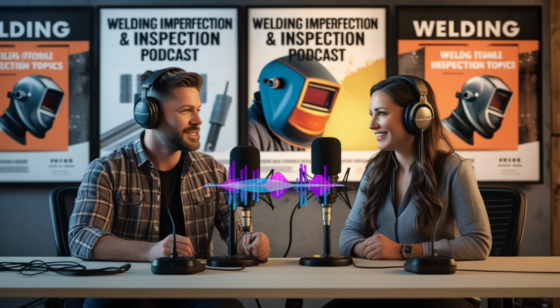Cleaning again. Always. And in certain welding modes, like the short-circuiting transfer mode in MIG-MAG welding, having excessive inductance in the welding power source circuit can sometimes lead to a colder, less fluid weld pool that's more prone to lack of sidewall fusion. Okay. And what about lack of inter-run fusion between those passes in a multi-pass weld?